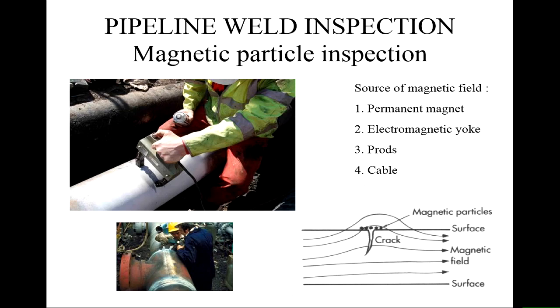to close. So if you then spray a magnetic particle onto the surface, so an iron particle, they will tend to collect where these magnetic field lines come up over the surface. So if this crack is there, you'll get the magnetic particles collecting on top of the crack. The magnetic field, as I say, is normally electromagnetic, but it could be a big permanent magnet.